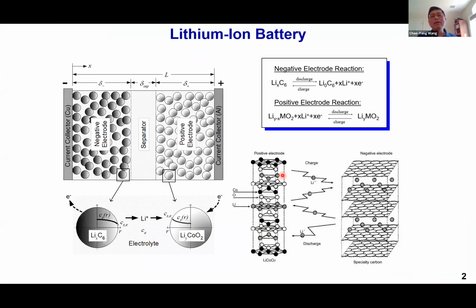Okay, so a lithium-ion battery involves basically an anode and a cathode and then an electrolyte in between. During charge and discharge, you have lithium ions shuttling between the two electrodes, and this is how the lithium-ion cell works. A common material for the anode is usually carbon or graphite, whereas the cathode may consist of layered metal oxides, or lithium iron phosphate. Both electrodes involve what we call intercalation reactions, where the lithium ions can be inserted or extracted during charge and discharge.